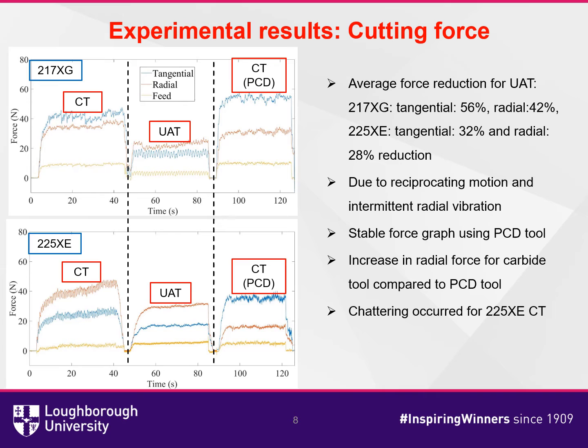The radial force for 225XE was higher than tangential force using carbide tools for both CT and UAT. Slight chattering was happening on both CTs for 225XE, which caused higher fluctuation of the forces.